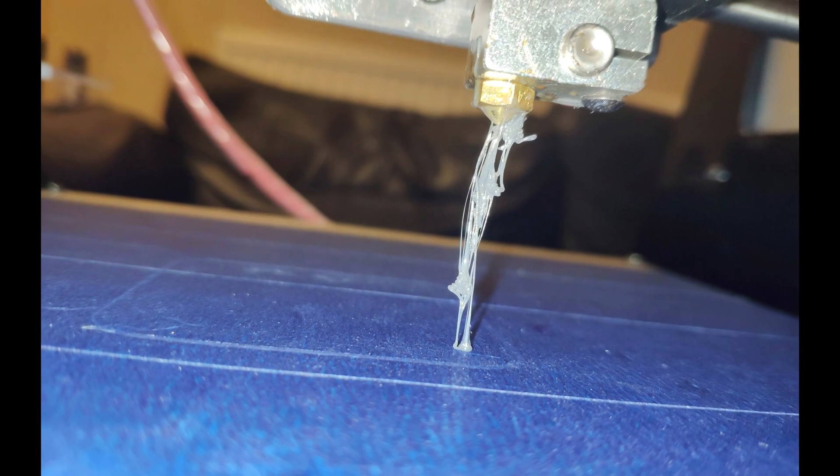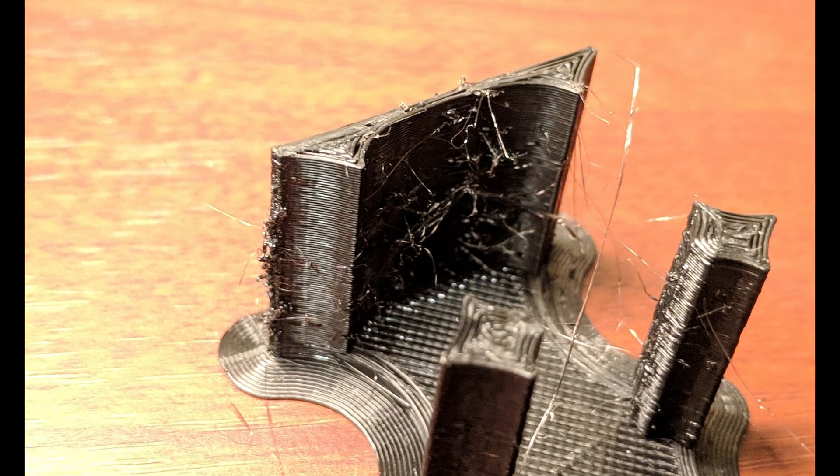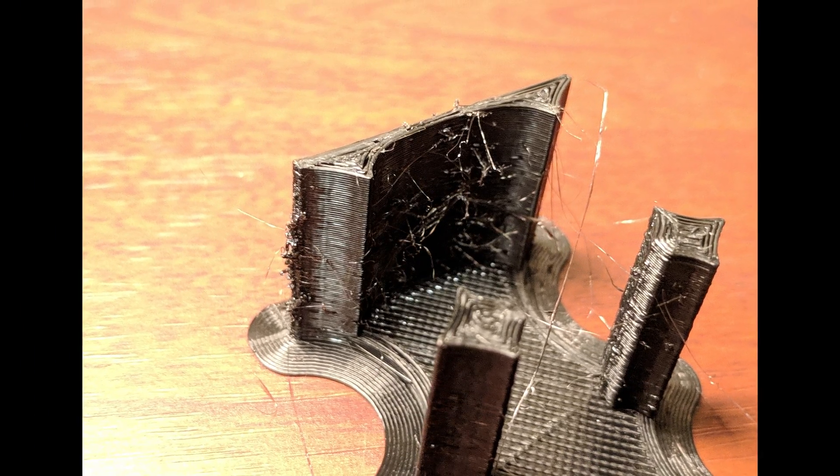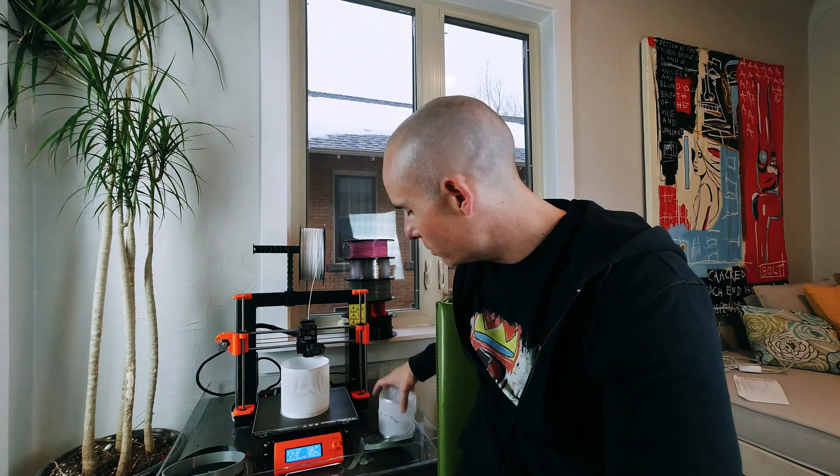I started printing with it and it's a little bit different. You have higher printing temperatures, 230 to 250 degrees Celsius, higher bed temp, usually 72, I've seen people go up to 110 degrees Celsius. It also sticks a lot more, so if you have a brass nozzle the PETG can actually stick to the nozzle and causes globbing. The first layer is typically a little bit thicker so you need to go higher on your z-axis to get that nice first layer. If you don't get all of that right, what ends up happening is what you see over here: this big pile of mistakes, pile of sadness as I like to call it.